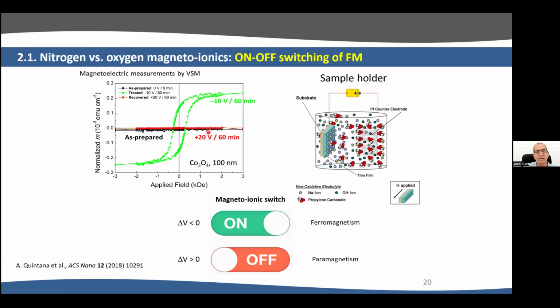And then if you apply 20 volts for another hour, you recover the paramagnetic state, this red curve here. So we called this a Magneto-Ionics switch because we can switch on and switch off the ferromagnetic properties of the material in a similar way as one could switch on and off the light of a lamp. So that's an interesting effect, but the problem here is the speed. You see that we need 1 hour to switch on and to switch off. So in the following, what we did is to try to reduce this time significantly.